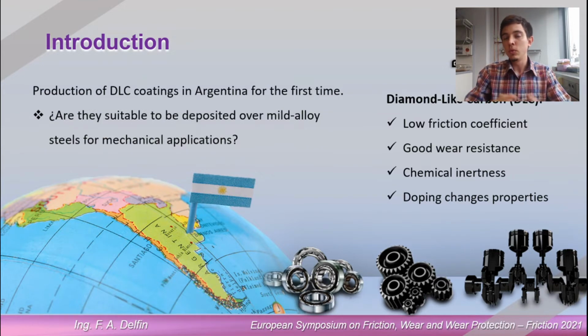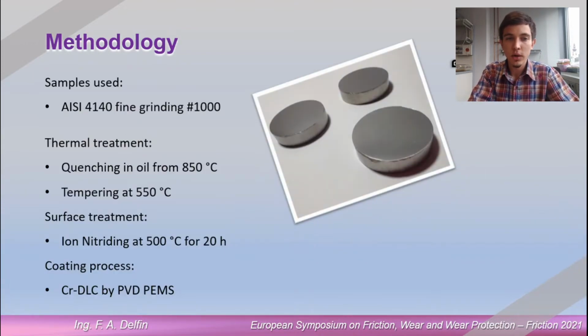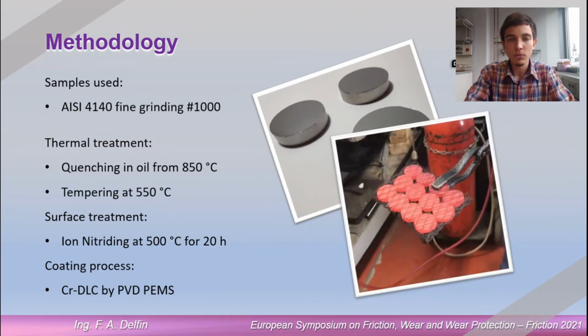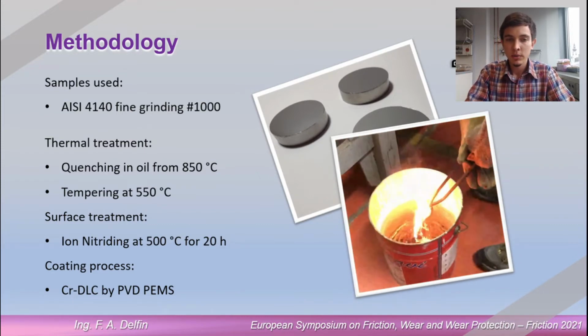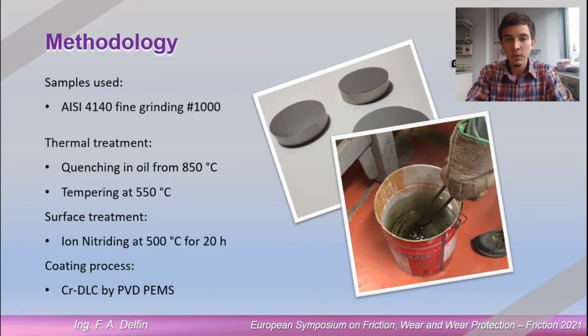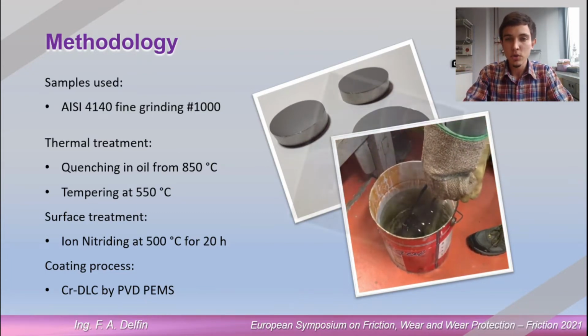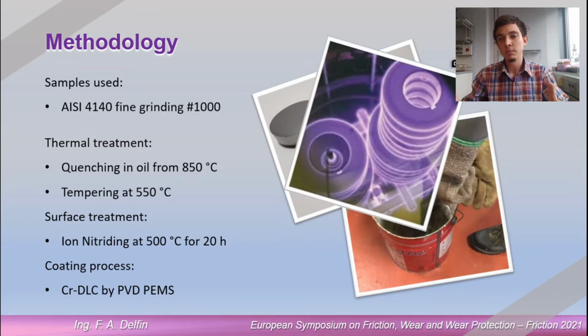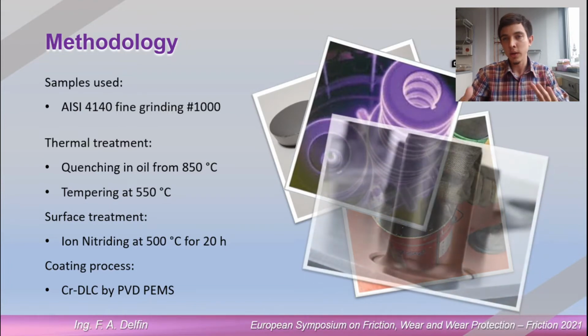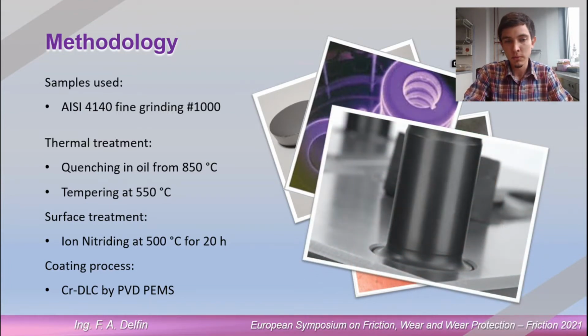What we want to do with these DLC coatings is to deposit them over mild alloy steels for mechanical applications, because we want to reduce friction, energy consumption and gas emissions in different mechanical applications. So for this work we use AISI 4140 samples, or 42CrMo4, or 1.7225 as you may know it. We did a thermal treatment with quenching in oil, then tempering at 550 degrees, which is a really high tempering temperature. So it's a lower hardness but really high toughness of the material, so we know it can withstand a lot of mechanical forces.